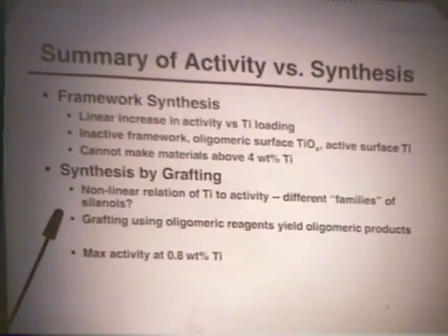Grafting, it appears that either there's different families of silanols on the surface that provide different reactivity and hence then different eventual activity for oxidation, or there's different sorts of titanium coordination geometries as one grafts. And grafting using oligomeric reagents yields oligomeric products, probably not surprising.